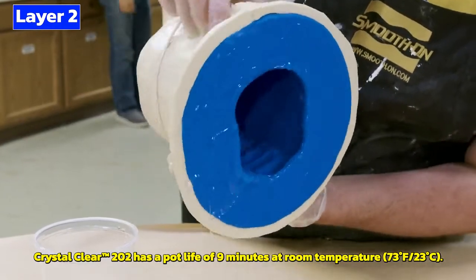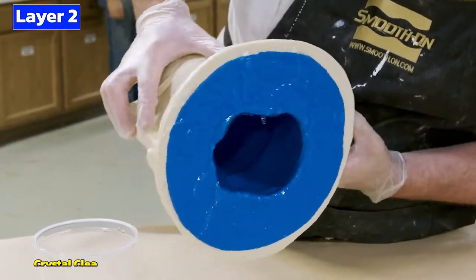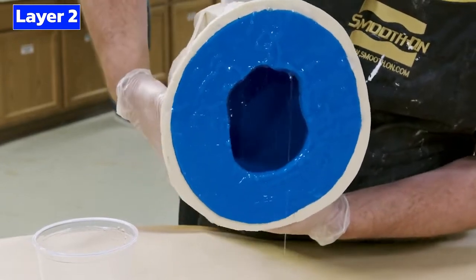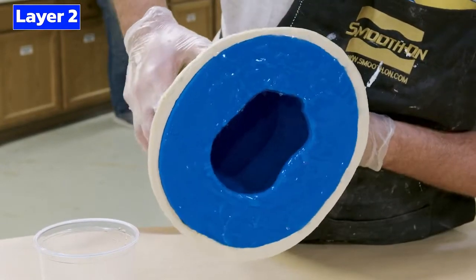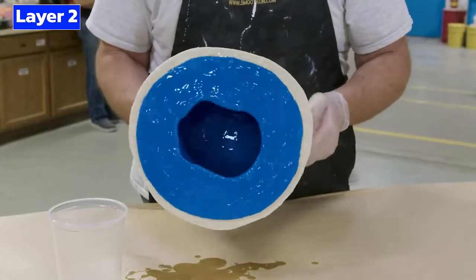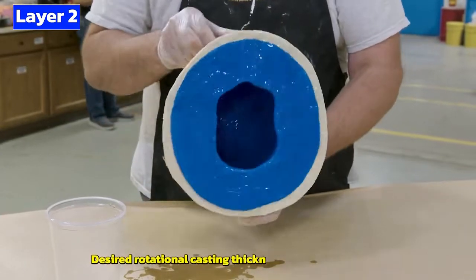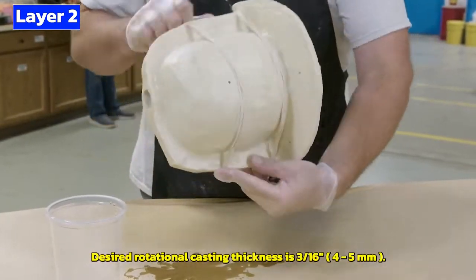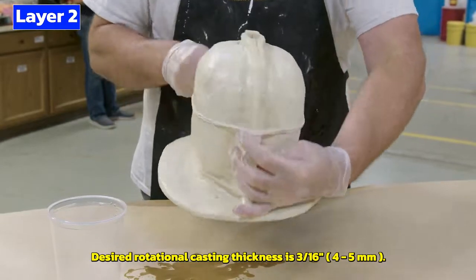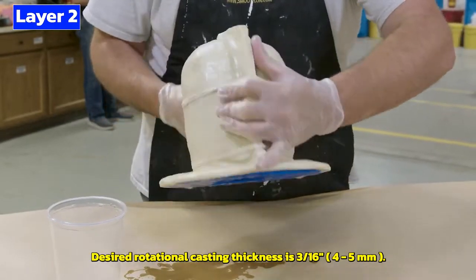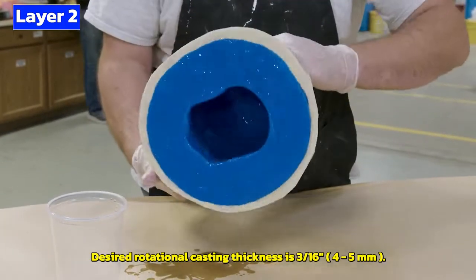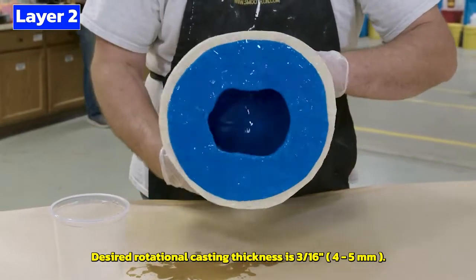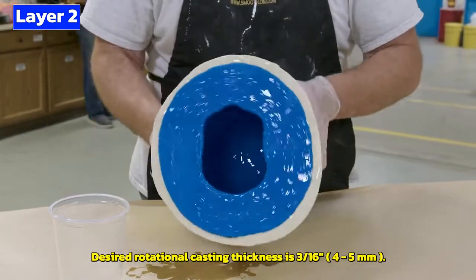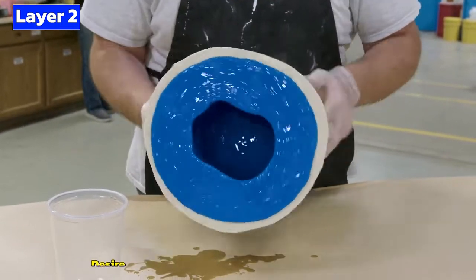The strength of our project here will depend on the thinnest area, so we want to make sure to spread the material and create an even thickness all throughout. The ultimate thickness that we're aiming for this project is about 3/16 of an inch or somewhere between 4 or 5 millimeters. That will give us sufficient strength for a small hollow rotational casting object like this.